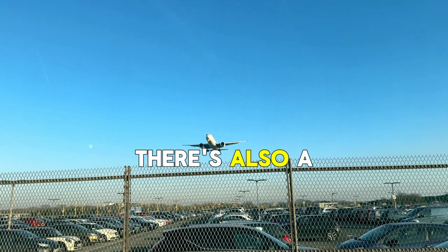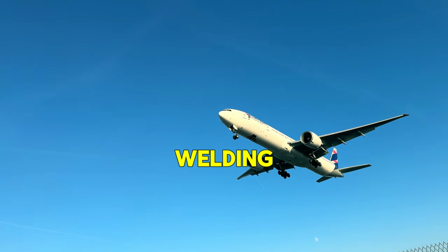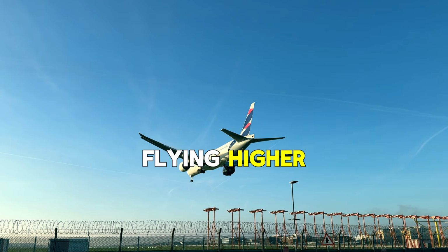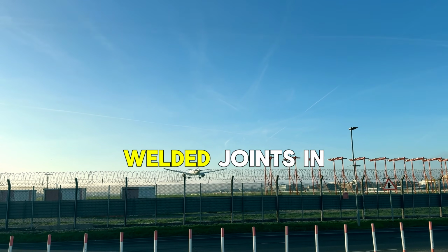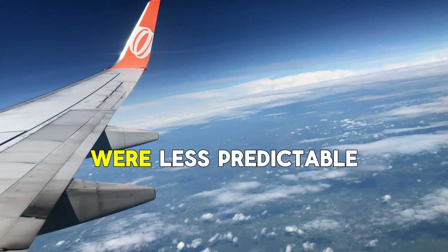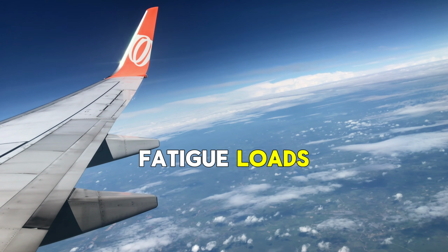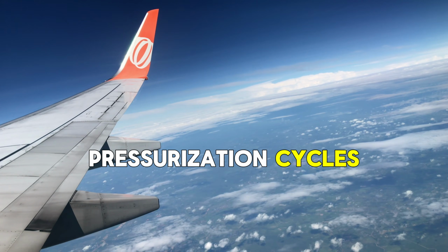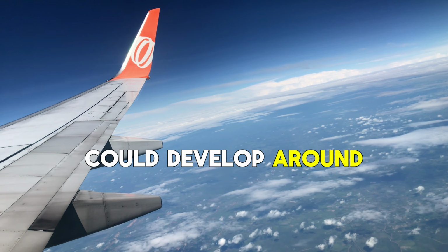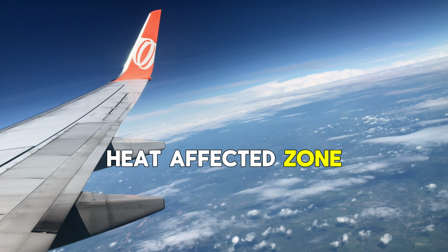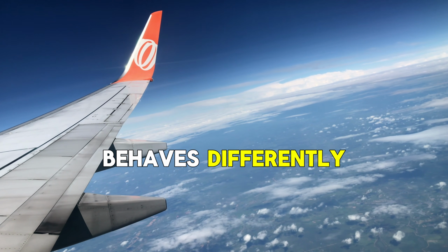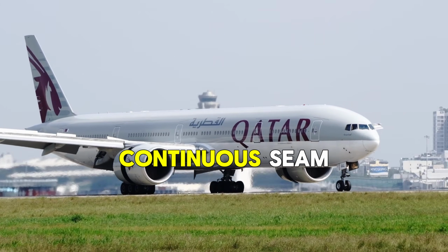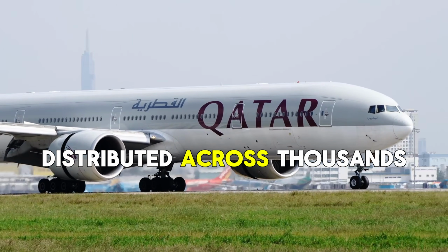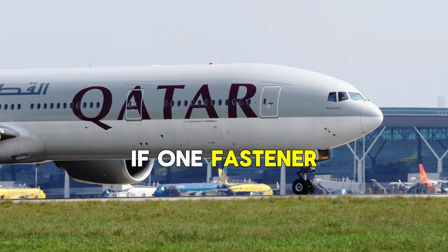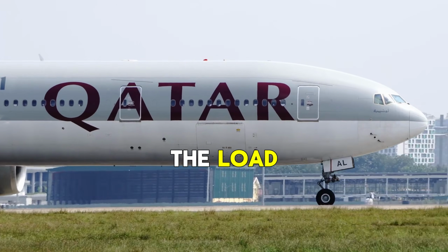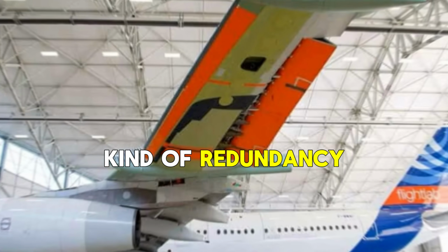There's also a historical reason why aviation moved away from welding. As aircraft started flying higher, faster, and farther, engineers discovered that welded joints in thin fuselage structures were less predictable under long-term fatigue loads. Over thousands of pressurization cycles, microscopic stress concentrations could develop around welded areas, especially in the heat-affected zone. A riveted structure behaves differently. Instead of concentrating stress along one continuous seam, the load is distributed across thousands of fastening points. If one fastener weakens, neighboring ones can partially share the load. In aviation, this kind of redundancy is critical.